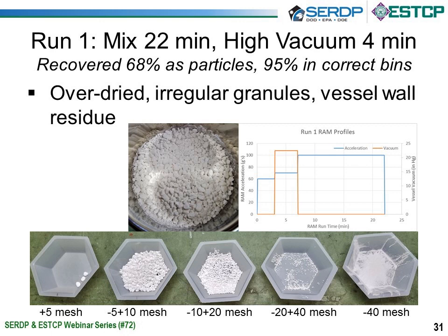As you can see here, we had overdried irregular granules, and the vessel walls did have some residual residue. But we are getting quite a bit of material in that minus 5 to plus 10 mesh and the minus 10 to plus 20 mesh that we were shooting for. Slide 32, please.